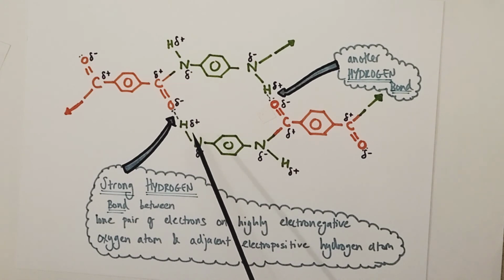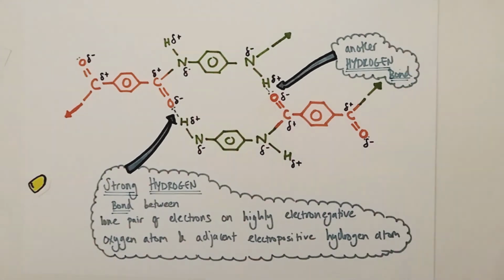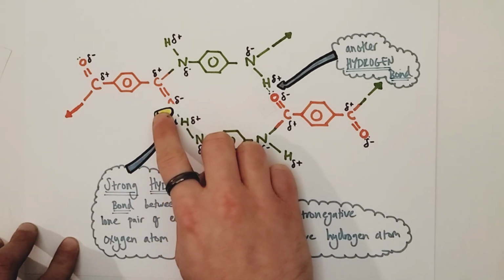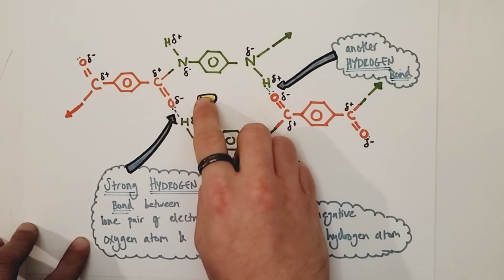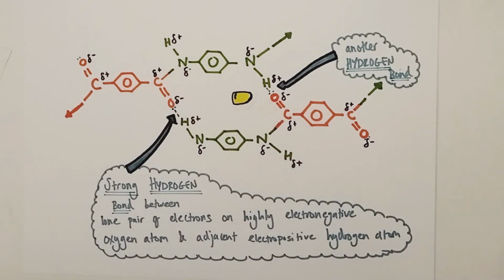These intermolecular forces hold the Kevlar fibers together incredibly strongly in tight, highly regular arrangements. When a high velocity round impacts the Kevlar, it finds it extremely hard to move the fibers apart to continue its forward momentum. And kinetic energy is rapidly depleting as it does so, slowing down the bullet and stopping it penetrating the layers of Kevlar.